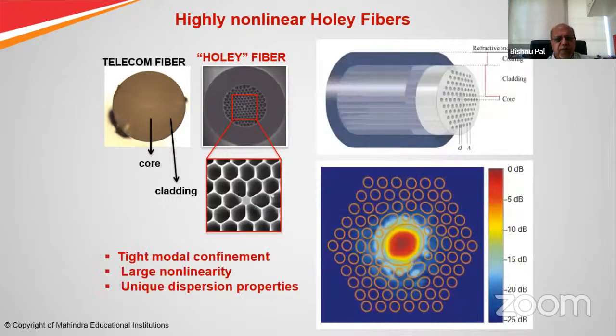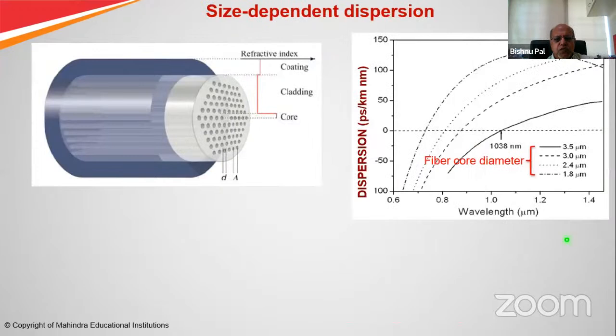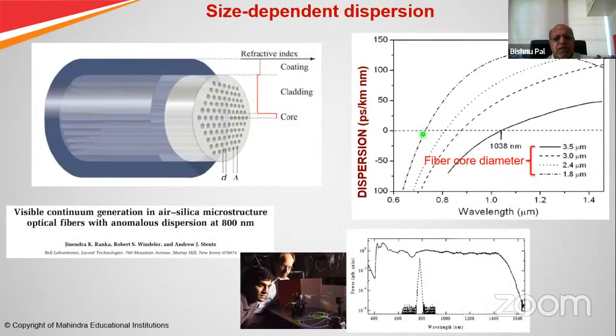If you consider such a fiber and look at its mode pattern, it looks like this. Let us not go into those details. Ultimately, what I wanted to show you is that you can control the dispersion in such a fiber by choosing the air core diameter of different dimensions. You can see that zero dispersion for one of these fibers is here, whereas another fiber of bigger dimension is shifted to somewhere here. So you design the fiber such that its dispersion is minimum at a wavelength where you will pump in high power laser light, a femtosecond laser.